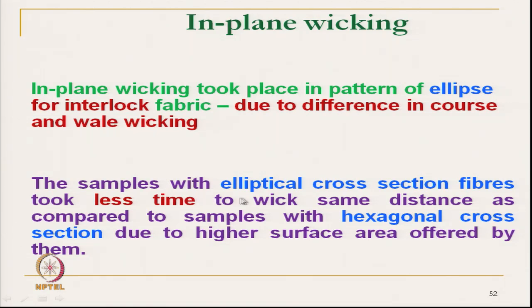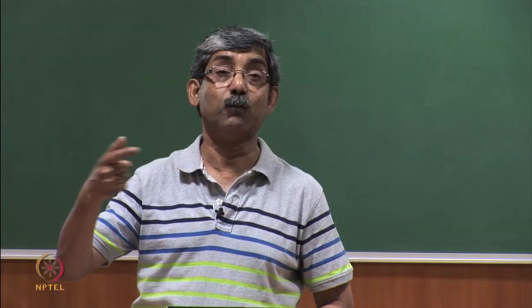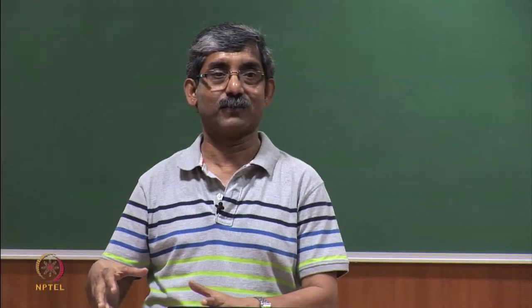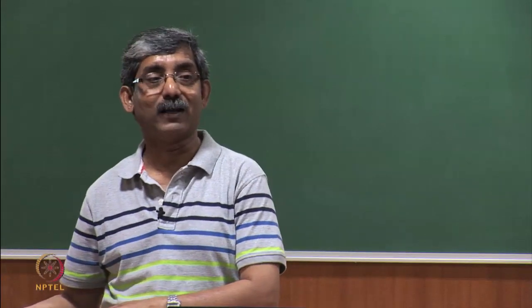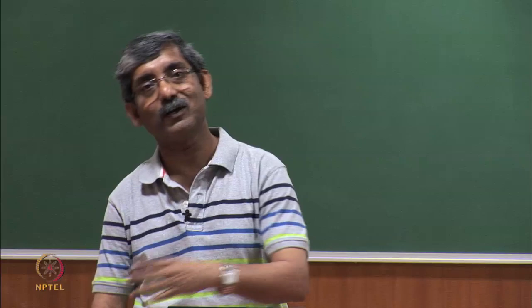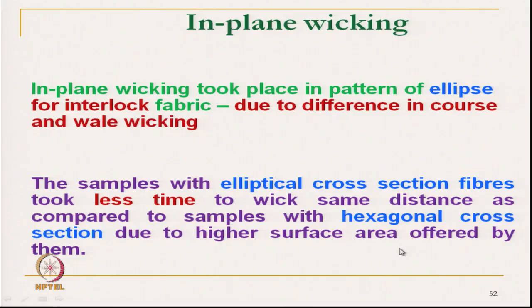The same phenomenon is predominant here, giving an elliptical structure in place of a circular one. The water front shape is elliptical here, and the sample with elliptical cross section fiber took less time to travel the same distance compared to the hexagonal cross section, due to the higher shape factor and higher surface offered. If the pore offers higher surface, the drag force will be high. So the drag force is also proportional to the surface offered by the fiber inside the pore.